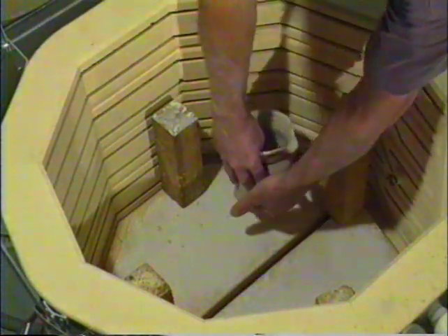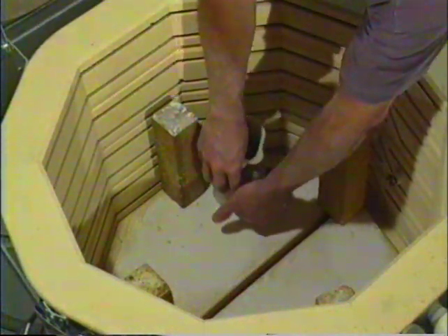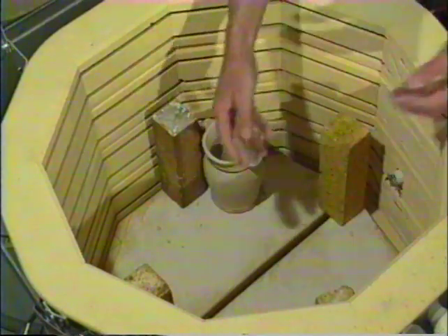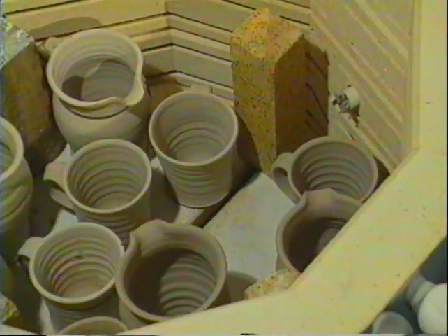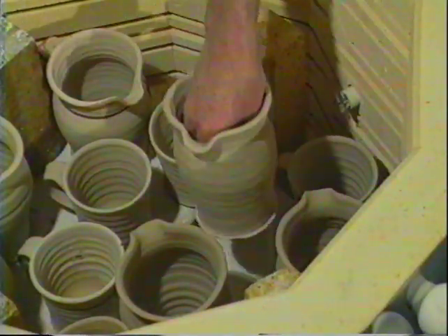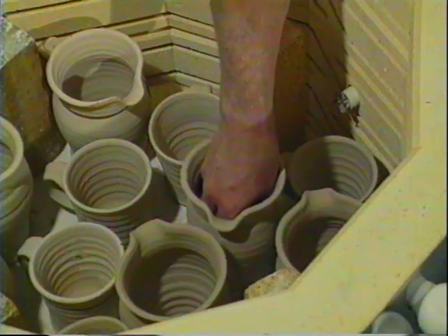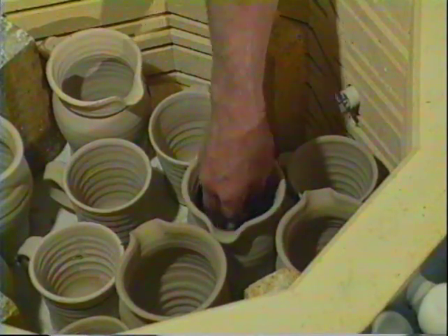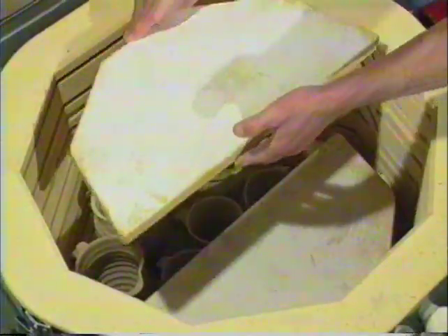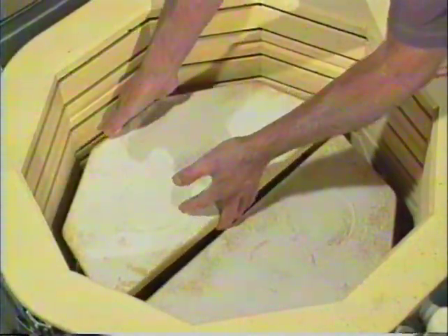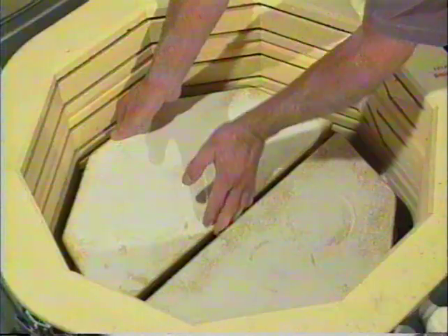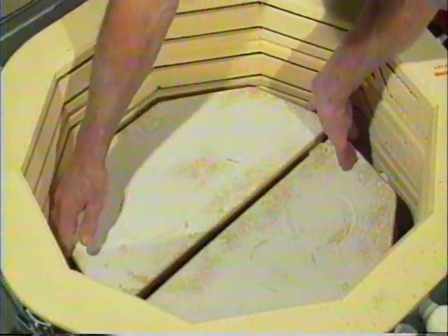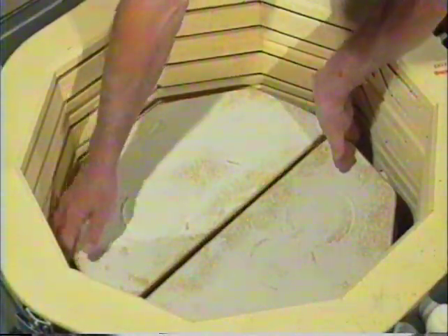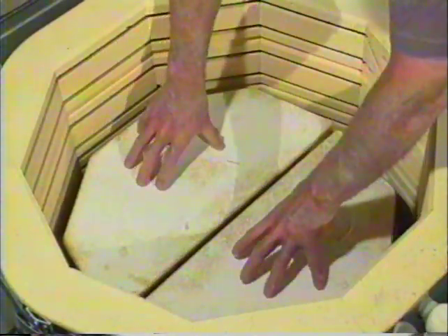And what you're looking for basically is to keep each pot about 3/4 of an inch away from its neighbour, 3/4 of an inch away from the wall of the kiln. A good fat finger width clearance all around. As you build this stack up, just got to be careful for stability that each set of posts and extenders that you use is directly above the ones beneath.